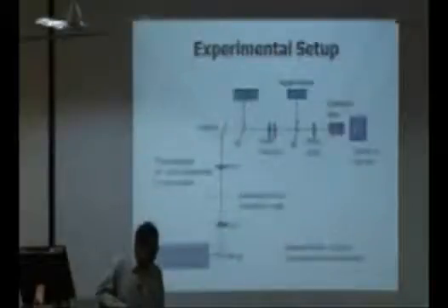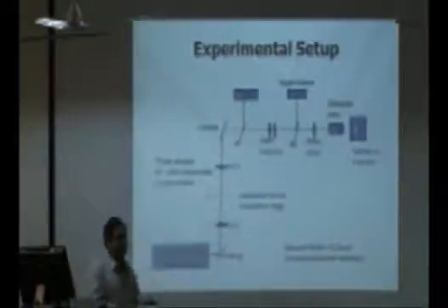So there is no contribution of the wetting layer in this case. We made these 400 micron by 200 micron mesas and then semi-transparent titanium top contacts, and then we did photocurrent measurements. What we studied is basically the Rabi oscillations in the photocurrent.